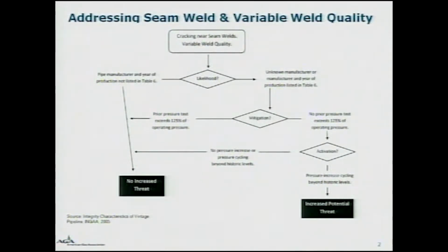This flowchart, taken from a 2005 report prepared for the INGAA Foundation on evaluating integrity characteristics of vintage pipelines, demonstrates how an operator can manage historic anomalies most likely to threaten a pipeline's integrity. In this particular example, which is addressing seam weld and variable weld quality, guidance is provided to identify when a defect may exist for a particular pipe type and vintage, conditions that may activate a defect, and practices used to mitigate the potential threat. One method of mitigating the risk due to cracking near seam welds is to pressure test. Another is to perform inline inspection with a tool designed to detect cracks. The bottom line is that operators have to make decisions based on specific pipeline threats, as each assessment technique has limitations.